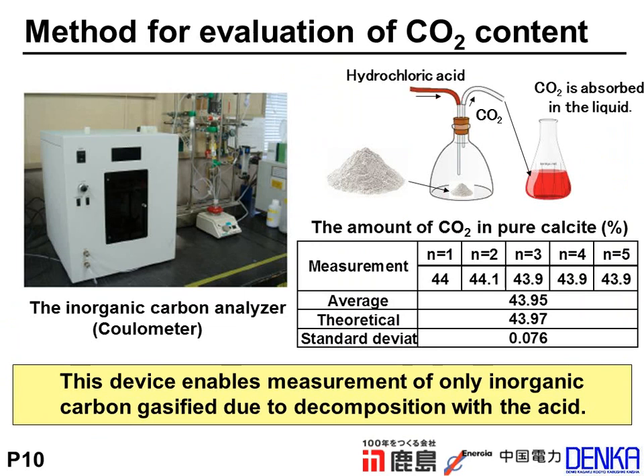The right table is a measurement result of the amount of carbon dioxide in pure calcite. The theoretical value is 43.97%. On the other hand, the average measurement value is 43.95%. So you can see that this device has good accuracy to detect the carbon dioxide content.